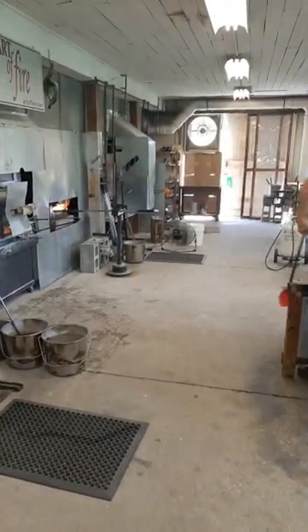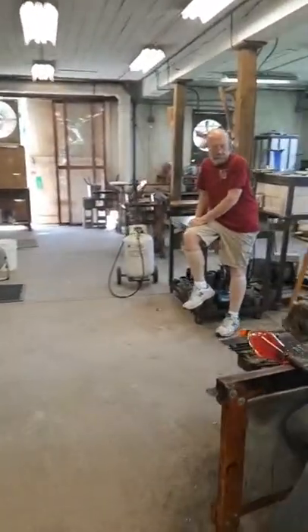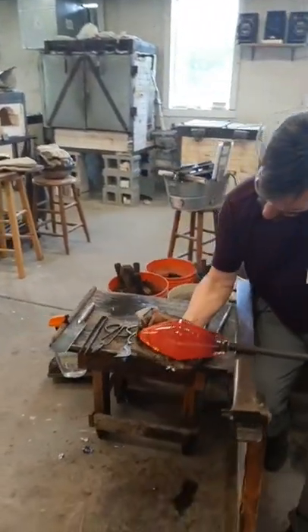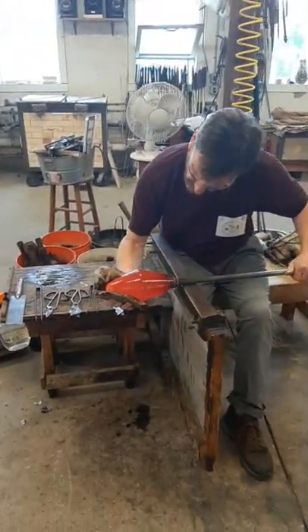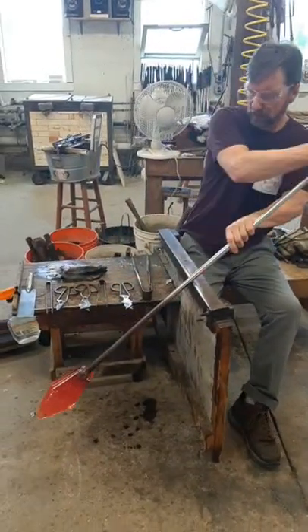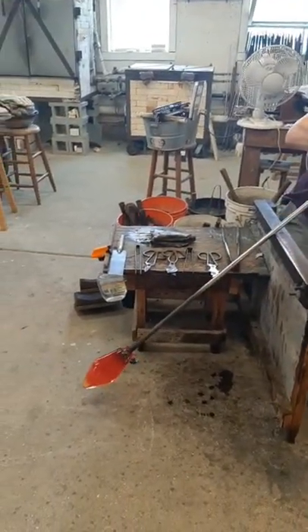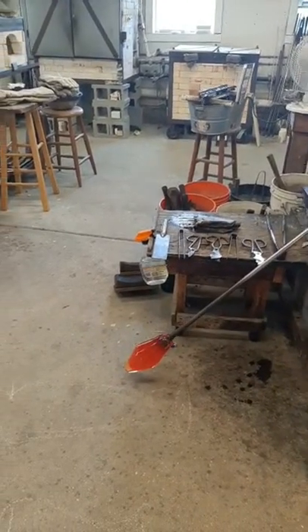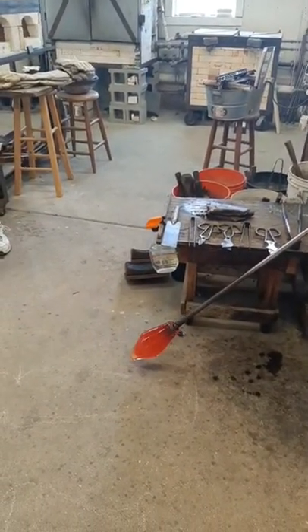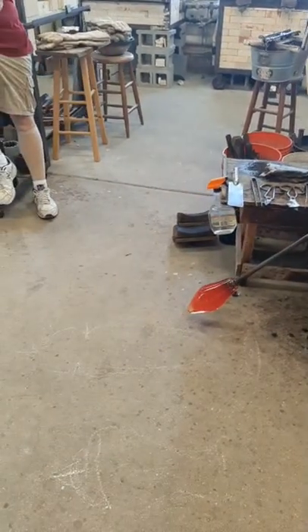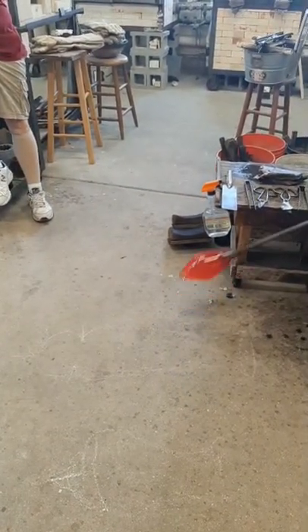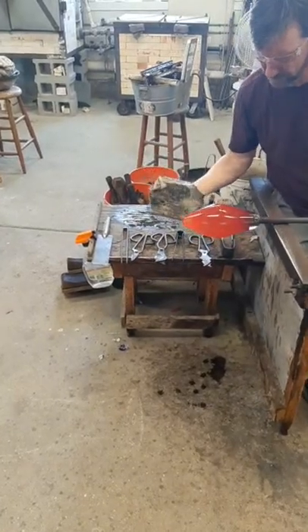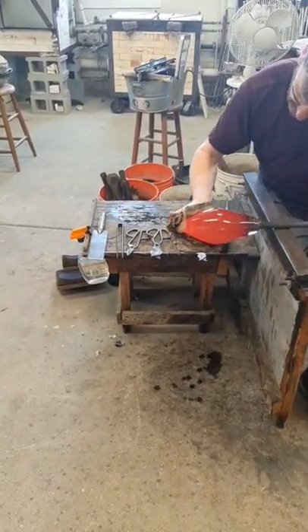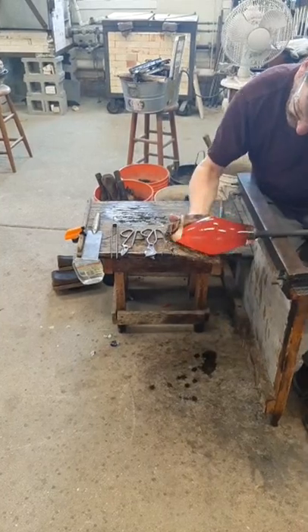He can go back and forth between those two, and he'll be going back for more reheats too. We use newspaper as a shaping tool. If you use about 7 or 8 sheets of newsprint, fold it up to about a 7-inch square and keep it soaked in water, it's a perfect insulator. Notice that the glass is inflating in the middle and the upper regions, but not the bottom of the piece, which is that outboard end, because Todd has cooled it with the newspaper and previously the marver.